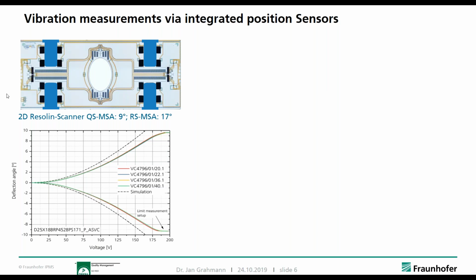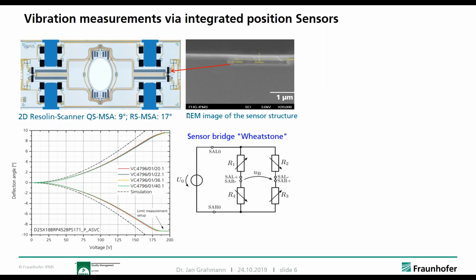And that example is shown for a scanner that is quasi-static on this axis and resonant on this one. And below you see a graph that shows that we achieved here about ±9.5 degrees deflection, meaning 9.5 times 4 degrees field of view for that quasi-static axis, and 17 degrees on the resonant axis, which also has to be multiplied by 4 for the field of view. So that piezoresistive sensor is located quite near the actual anchoring of the torsional springs, and, classically, as known from pressure sensors, it changes its resistance with the stress, respectively strain, it sees from the movement of the scanner. That is read out by a Wheatstone bridge for the scanner.